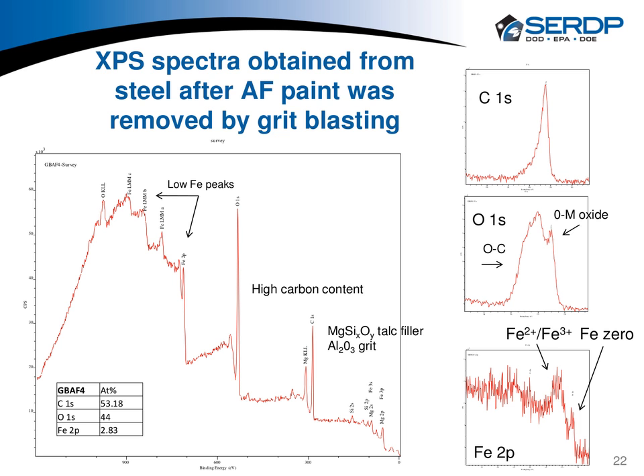Okay, coming back to the chemistry. Hopefully you're familiar with X-ray photoelectron spectroscopy. This is a very surface-sensitive technique. It only looks at something like 50 to 100 angstroms of a surface, so we're looking at, on the order of, 10 or 20 chemical bonds. Very, very surface-sensitive. This first spectra was obtained from an anti-fouling panel that was depainted by grit blasting.